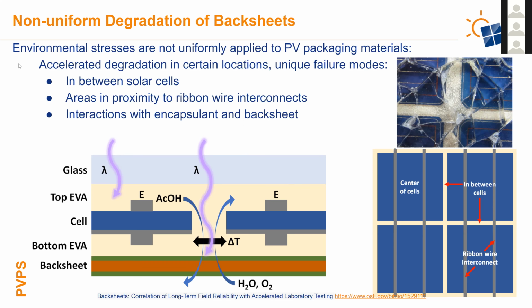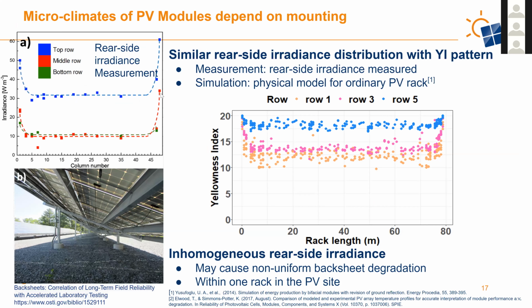And when we measured rear side irradiance, you actually see the same exact pattern, where rear side irradiance on the back that's reflected off the ground and back onto the backsheet is actually higher on the edges and at the top of the module rows in this case.